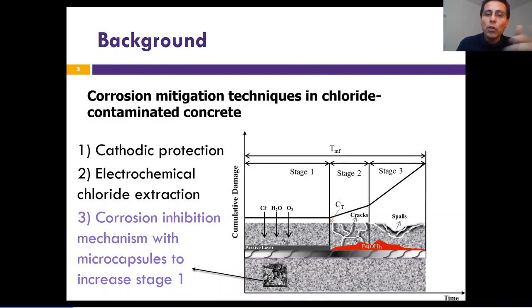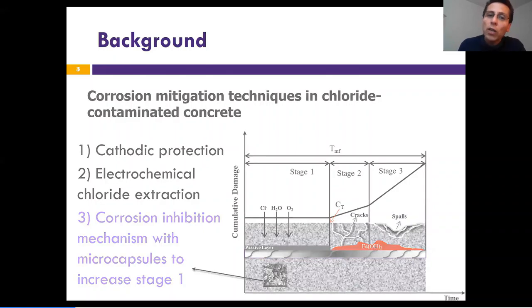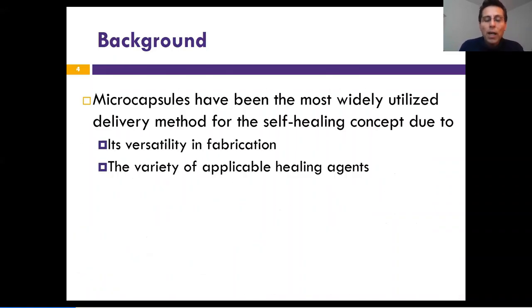But what we can do is, again, extend the life of each one of the stages, in this case, stage one. Therefore, the solution that we are proposing in this topic is the inhibition mechanism in the concrete. The inhibition mechanism is by microcapsules. The microcapsules are embedded in the concrete as an admixture, as an additive, sorry.